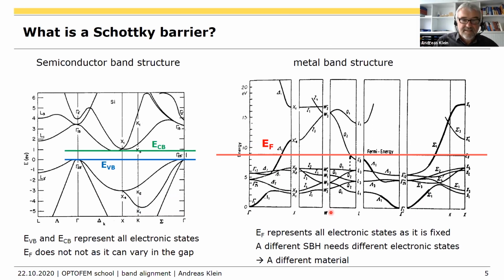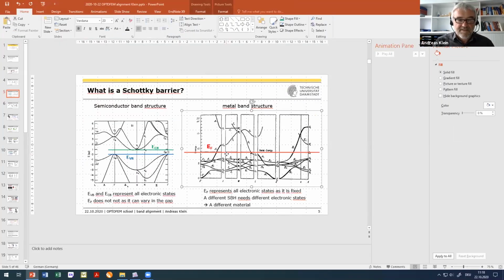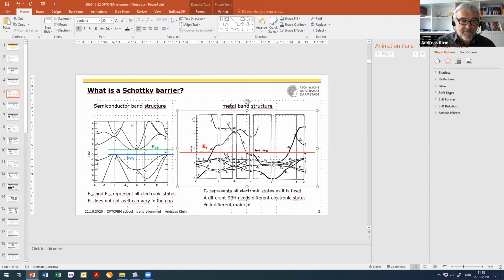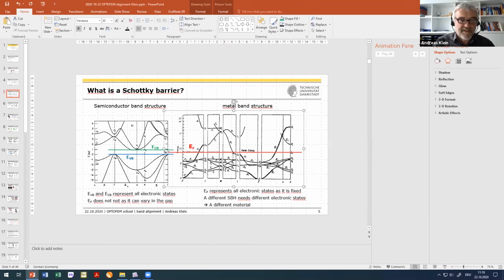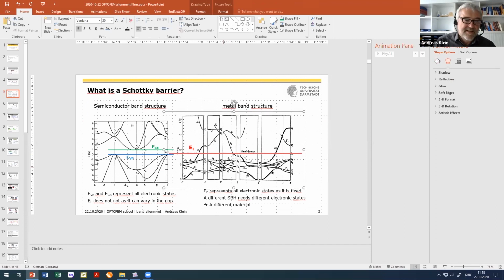And now we make the contact, and I have to leave the presentation mode now. Sorry. Because now we go into contact. So we bring the Fermi level somewhere in the contact with the semiconductor. And if you would change the Schottky barrier height, that means you would have to change all electronic states. You can imagine that that's not easily done. That means you have to change the chemical bonds at the interface. Or in principle, you change the electronic states at the surface.